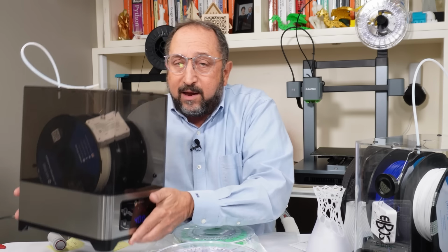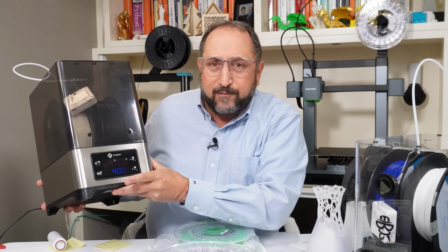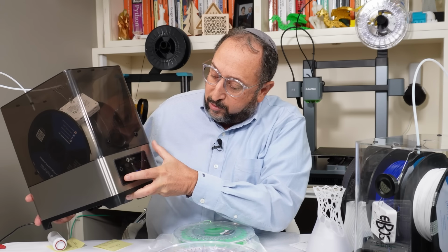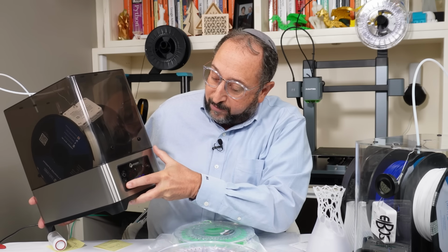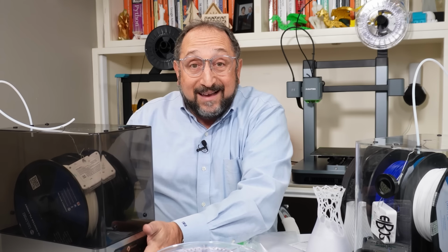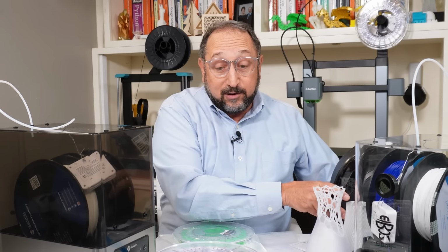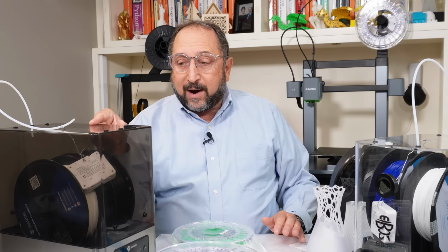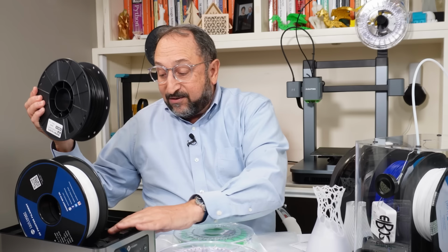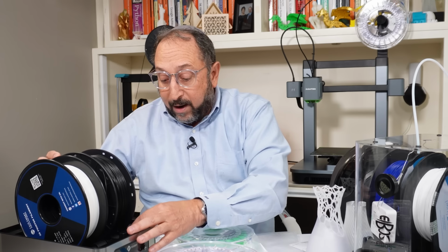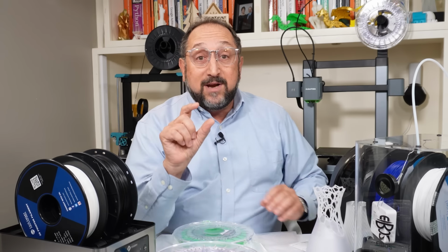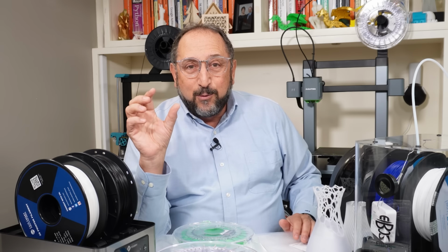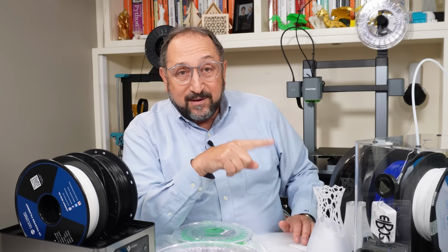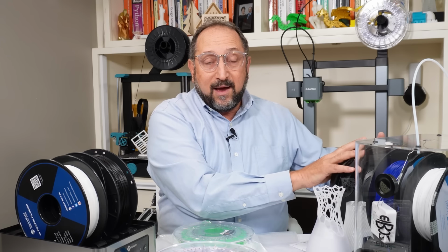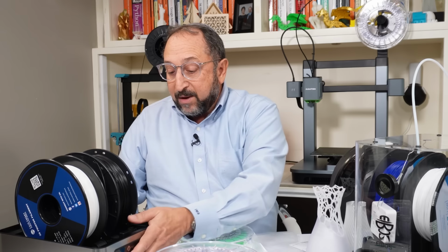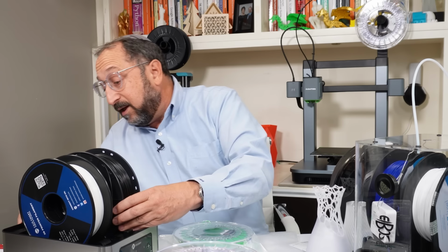It has also a nice front panel. I don't know if you can see that here. And you can cycle through the various options here on the front panel. It works quite well. It's a simpler display than the Sunlu. One of the limitations of this print dryer is the structure. These sit on rollers here, which are quite nice, but they were a little too narrow for the Prusa reels of filament. Whereas the Eibos was able to handle the Prusa and the Sunlu was able to handle the Prusa. The overall fit and finish of this device is really quite nice.